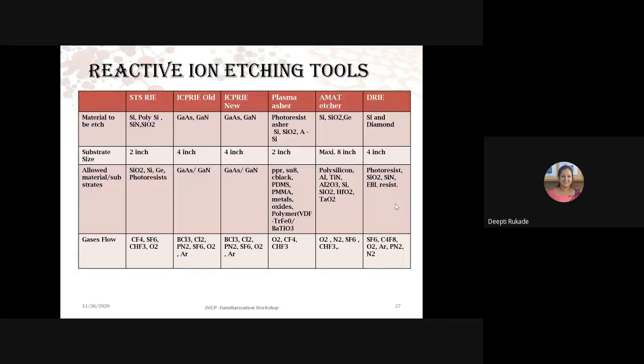We have a few dry etching tools also at IITBNF, which are summarized in the next slide. Here we have STS RIE, ICP RIE, plasma etcher, AMAT etcher, and DRIE. These different reactive ion etching tools have different gas compositions and different power bias, so that they can etch different materials, as you can see. For example, with STS RIE you can etch silicon, polysilicon, silicon nitride, and silicon oxide for 2-inch wafers. We have all the standard recipes, optimized for these particular materials, and those are on our website. Then you have ICP RIE, which is dedicated only to gallium nitride and gallium arsenide. We have two ICPRIs in this case.